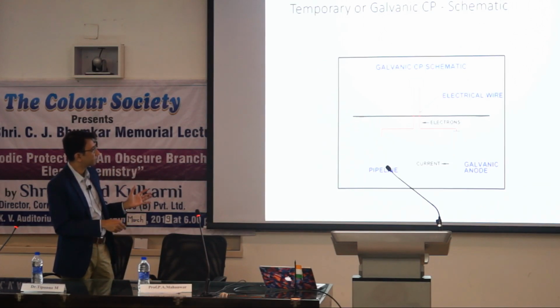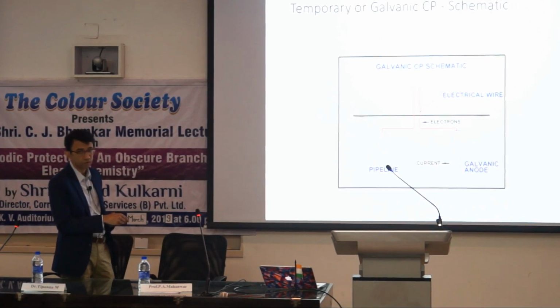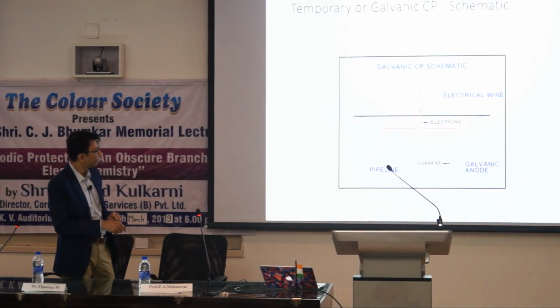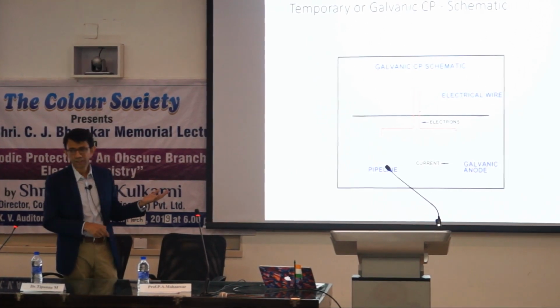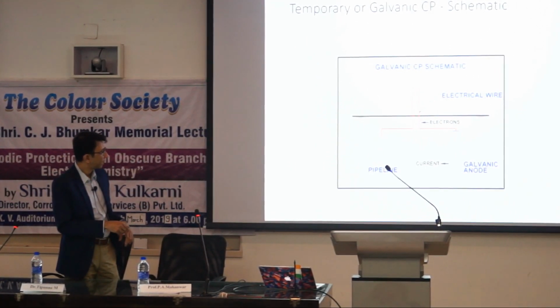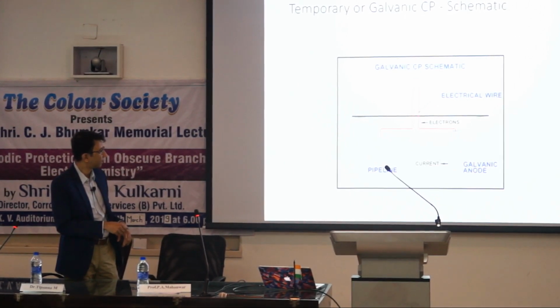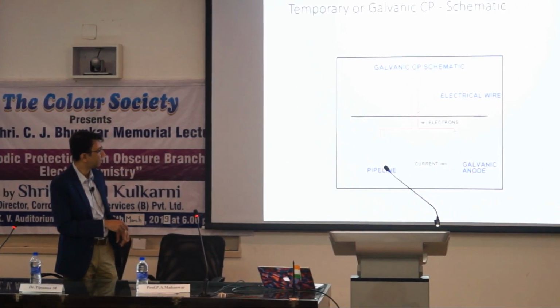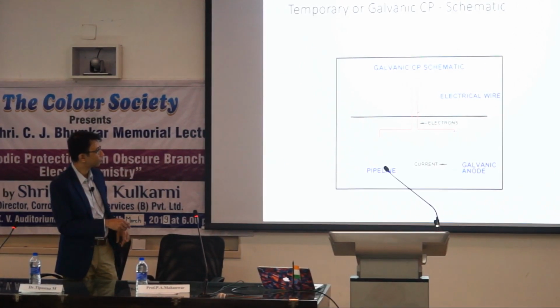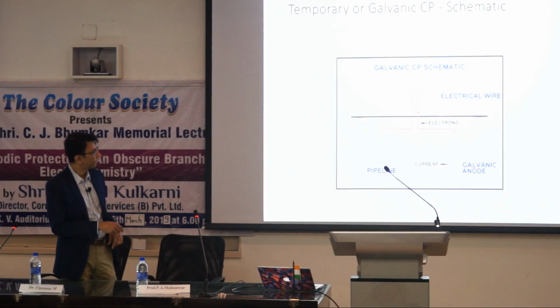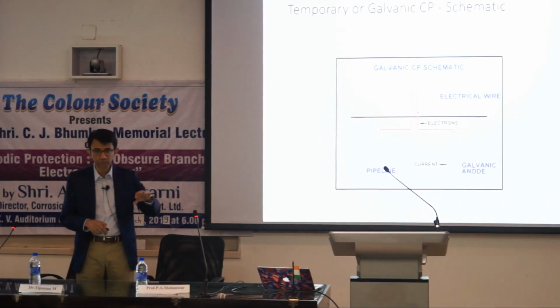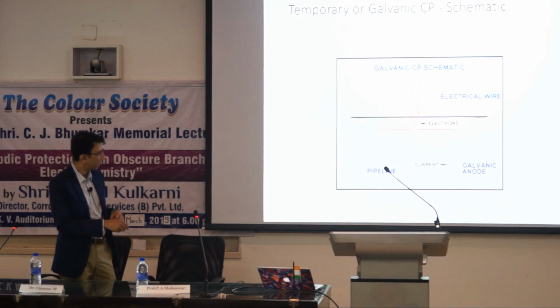Again, this is the same as the first galvanic cell that we saw. It's just that it looks different because we now have a real life example of a steel pipeline and an anode, and we have an electrical connection between them through a junction box or a test point. And we find that when we connect a galvanic anode, which is typically zinc or magnesium, we have the current being discharged from the anode into the surrounding soil, picked up by the pipeline, and returning to its source. So you have the galvanic anode getting consumed steadily, and the pipeline is protected.